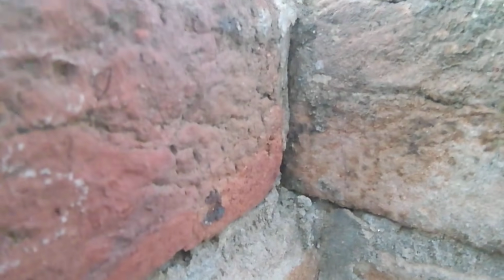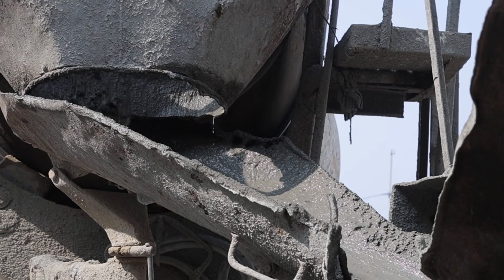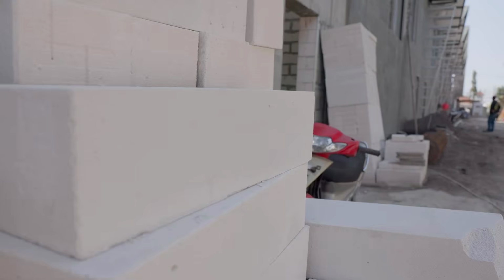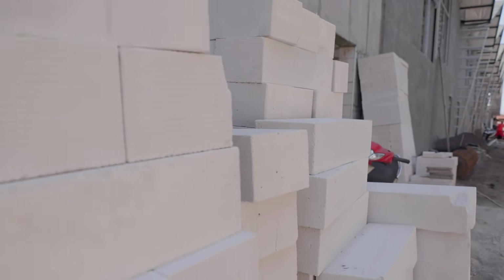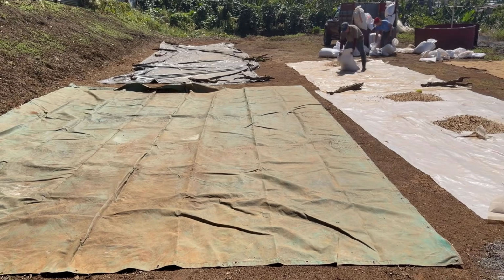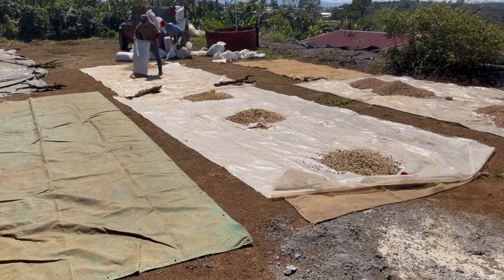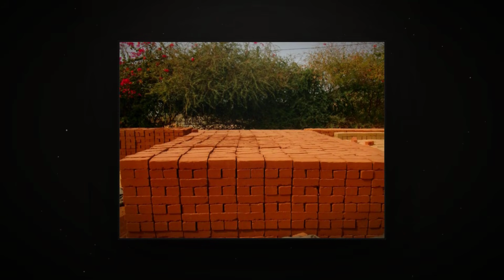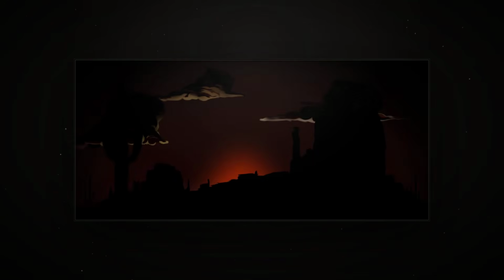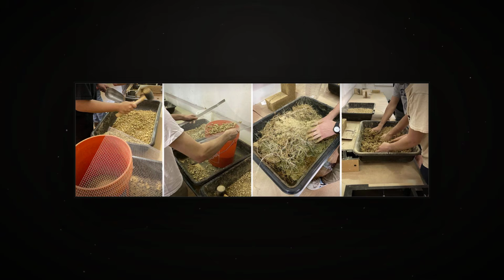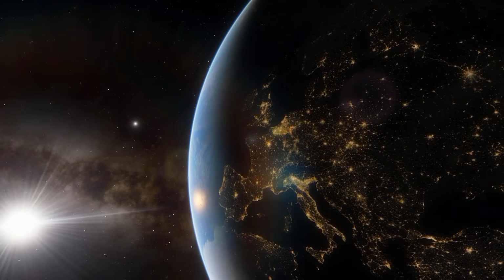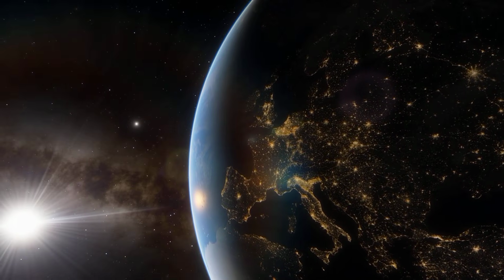The Portland cement in the mix isn't drying out, it's hydrating. That's a chemical reaction, not evaporation, and it requires water to complete. Expose those blocks to direct summer sun too early, say, uncovered on a flatbed in Arizona in July, and surface moisture flashes off in hours. The outer shell cures faster than the core. Micro cracks form within 48 hours, invisible to the eye, but they're there.